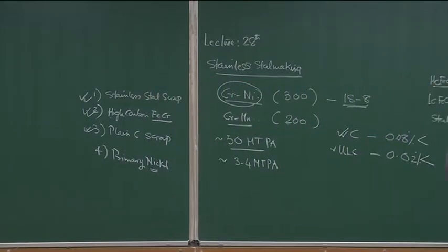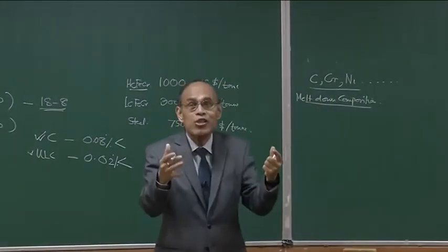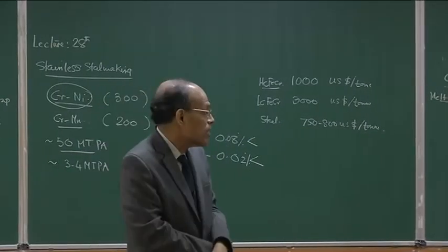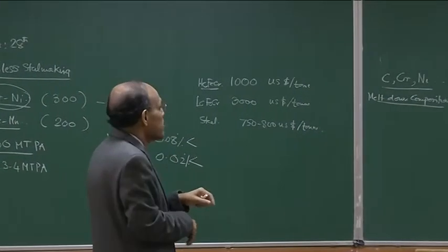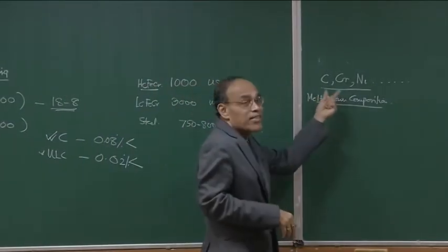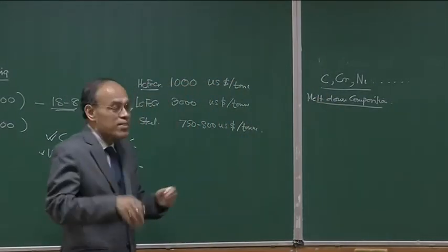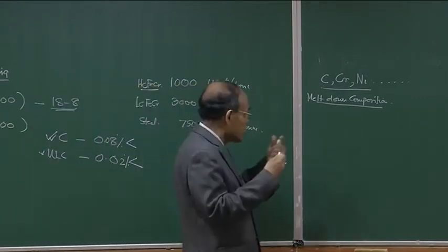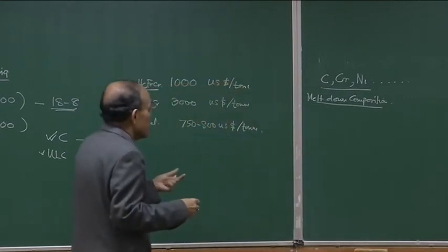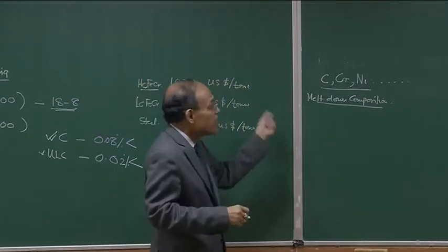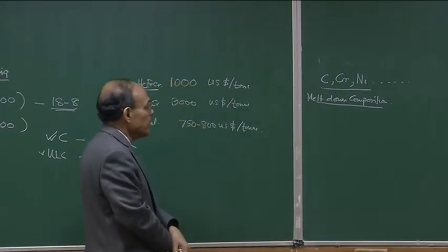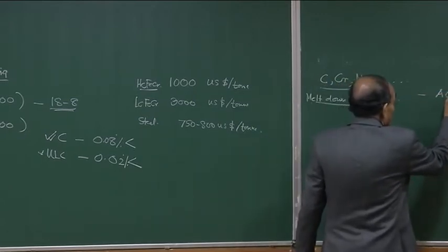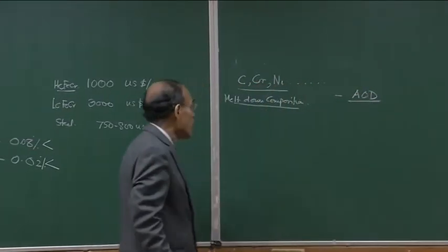Many special steel plants also produce stainless steels. So, in between production of various kinds of steel grades, one heat of stainless steel can be made in the arc furnace, where no slag is to be generated or made artificially. There you can just melt it and then transfer the melt into what is known as an AOD converter, argon oxygen decarbonization converter.